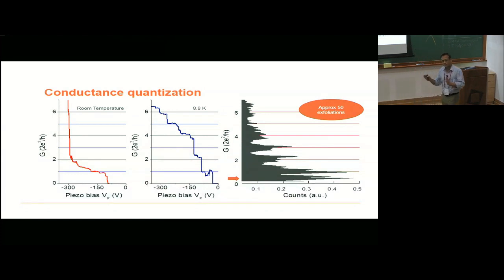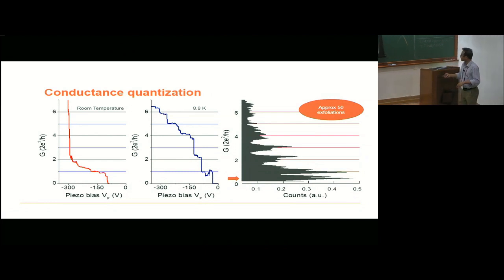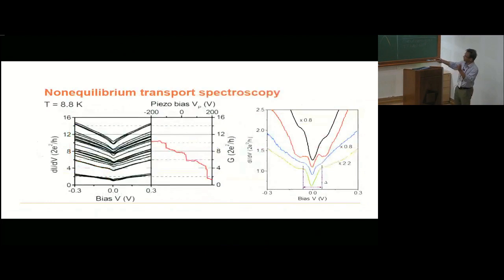This is something which we will come back to a little later. I'm going to move to this, which is something we did a little bit of: dI/dV characteristics, which is essentially the low energy density of states. You can see a small gap opening up at low temperatures, probably saying that the edge conduction along the graphene zigzag edges is determined by the strong Coulomb interaction.